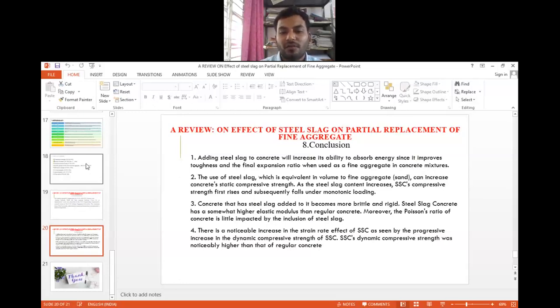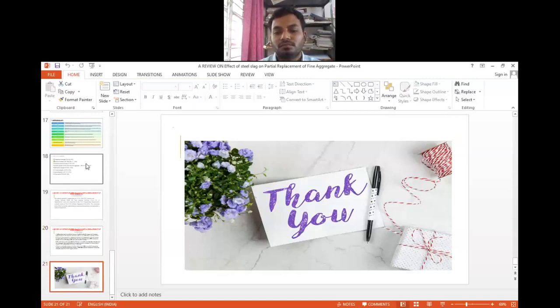There is a noticeable increase with strain rate. Steel slag concrete shows a progressive increase of dynamic compressive strength, noticeably higher than regular concrete. So I finally concluded that steel slag is a perfect match as fine aggregate, and optimum strength will be concluded in my further studies. The future scope will be explained after my research completion. Finally, thank you for giving me this opportunity.